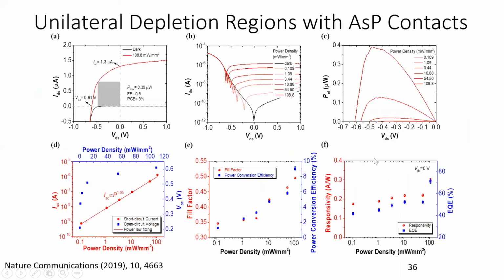And then I'm going to skip over this real quick, but you can actually get photovoltaic performance where you can get fill factors of about 0.5, and power conversion efficiency approaching 9%, at least under 10 suns, right? It is still concentrated power, but you are able to see open circuit voltages reach about 0.6 volts and power conversion efficiency reach close to about 9%. And so this is again more promising, and we think that there is room, by contact engineering, to push this even further.